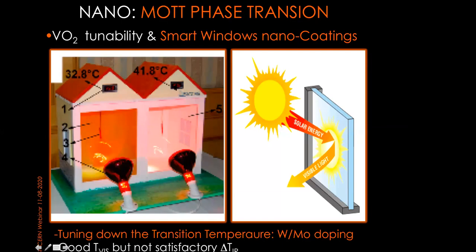And here, the temperature that you read with the thermometer inside the room here is nearly 42 degrees Celsius. With the glass coated with that material, as you can see the thermometer, instead of 42 degrees, it shows 33 degrees Celsius, which is nearly 10 degrees difference. And this 10 degrees is a huge difference. It's an extremely huge difference in terms of the amount of energy. In this room here, if you have to bring this temperature down to 32, you have to use air conditioning. So here you don't use any air conditioning. It's free.